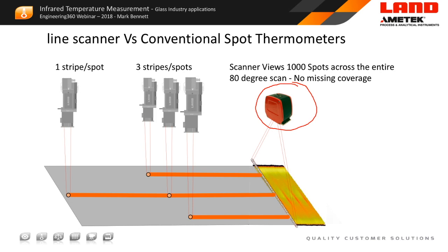Now, the beauty and the reliability of the scanner comes from the fact that we have a single detector here, so a single stabilized detector and a rotating mirror. So the same detector is measuring here as is measuring here and measuring here. So the relative temperature measurement is of very high repeatability and stability. Now, within the scanner, we actually measure 1,000 measurement points over an 80-degree scan. So we build up what is a very comprehensive thermal map of the actual process.